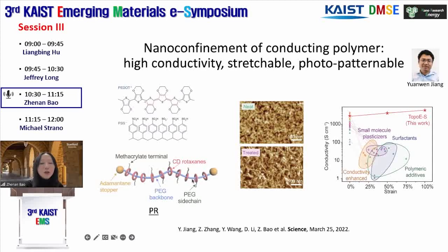But the PEG chain itself is crystalline. So just adding the PEG chain into PEDOT will result in a brittle film. That's why we had to thread the PEG chain through the cyclodextrin structure. And this allows the suppression of the crystallization of the PEG chain. And also, since these rotaxane molecules can slide along the chain, that provides a mechanism for dissipating mechanical strain. And then the side chains on these rotaxanes can be photo-crosslinkable groups such as methacrylate terminals, and this gives us all the properties that are desirable.